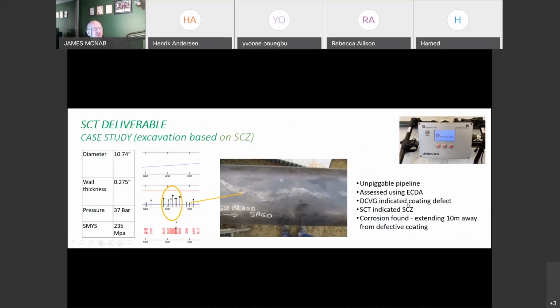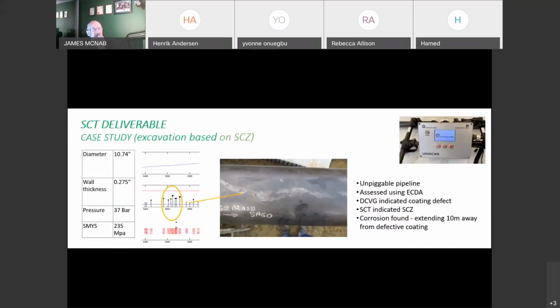Just as a quick one, the conventional large standoff SCT delivers the results in this type of format, where it highlights the stress concentration zones, which are in fact readings derived from the small magnetic field changes in a pipeline under pressure or not, or has seen pressure. This is actually called the Villari effect, and it's expressed in a percentage of the specified minimum yield strength.